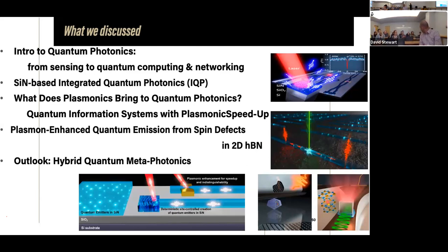No, that's the point. It has nothing to do with defects. We couple a single photon to this waveguide, we already did it, and we combine it with a resonator. It has Chi3, and the Chi3 is dramatically enhanced because the light travels many times. That could be used to generate entangled states, cluster states, and down conversion. So that's a key thing which we started to work on. I didn't mention it, but we already have first preliminary results using resonators in silicon nitride.